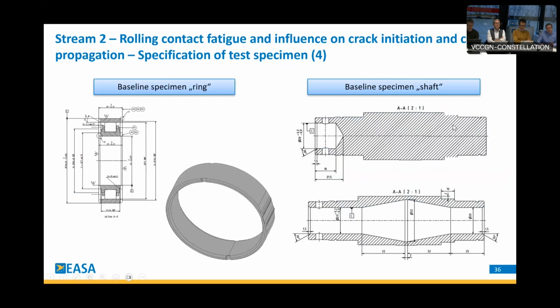Now we have just a few words about the test specimen. This test specimen ring, you see here a bearing, but the ring specimen is at the end the outer ring. This is the standard ring for phase 1, and for phase 2 in the complex load there is a CAD picture for illustration here. You see here on the outer ring the notch. So this is the notch which I mentioned, and this outer ring of the bearing is basically replaced by this modified outer ring. On the shaft, I think it's obvious here that we have a non-hollow shaft, a solid shaft, and a hollow shaft.